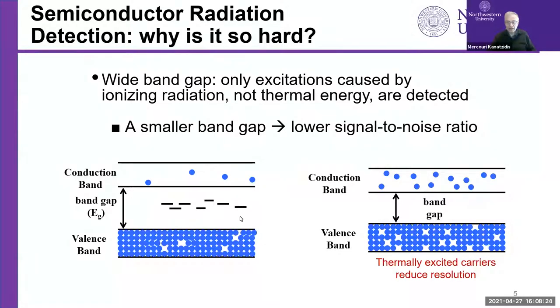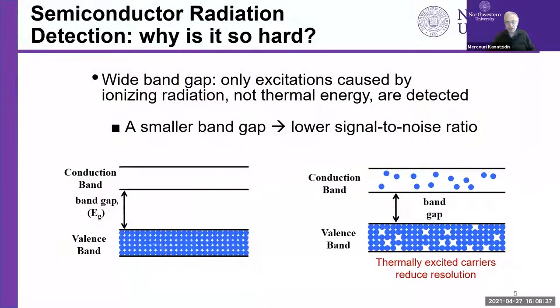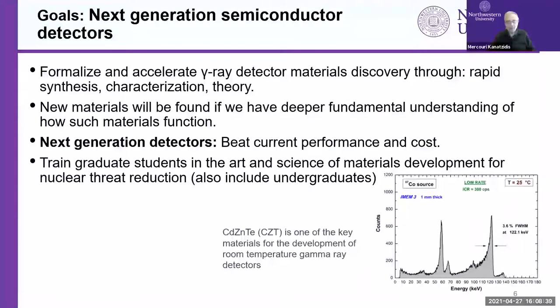And that is easier said than done because you don't have that many carriers generated. And so you have to purify the material extremely well, and that raises the cost and lengthens the time. So that's one big problem. So what we want to do is find something better than CZT and cheaper. So we want to match or beat the performance of CZT, which has been around for 40 years.